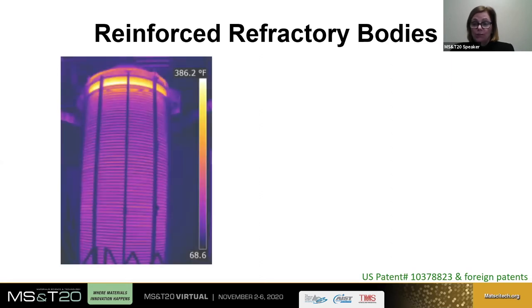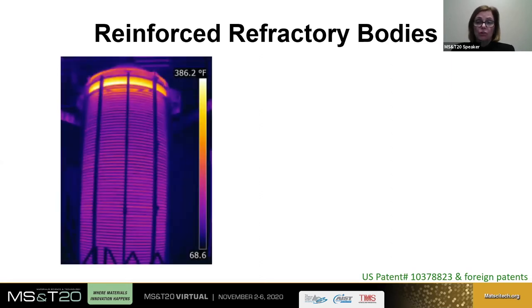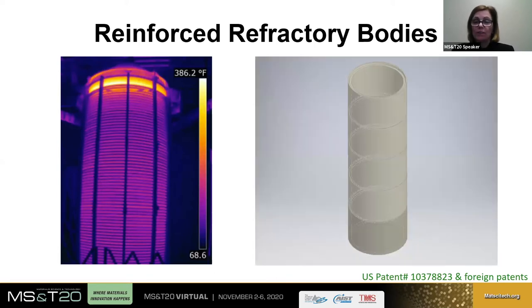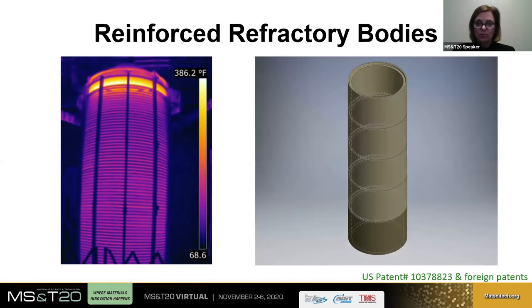This is an induction furnace for conversion of carbon to graphite. The carbonware is packed in refractory rings inside the induction furnace. The image on your left is probably 15 feet tall, maybe taller. The induction field converts the carbon to graphite. During various stages of the process, these rings can experience unbelievable thermal stress differentials from hot face to the outer cool face.